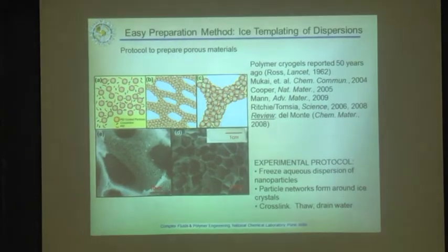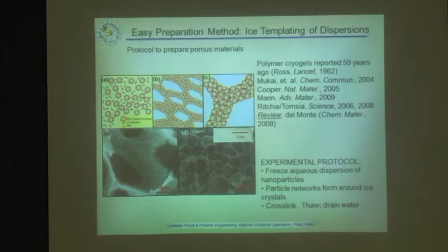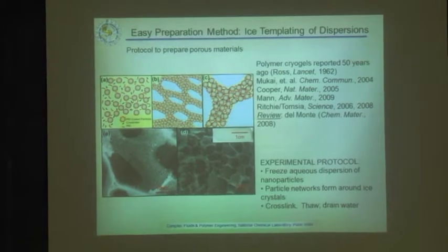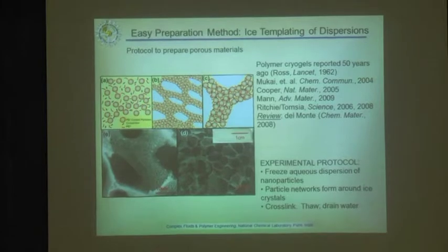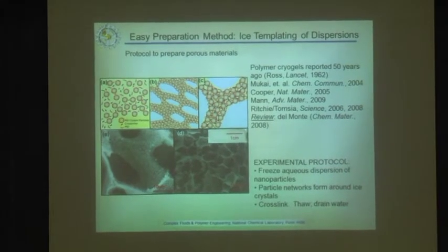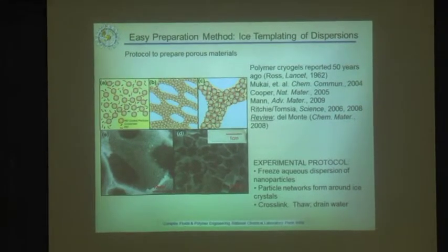The pore size also. The size of the pores might also depend on the rate at which you're freezing your... Absolutely. That is entirely dependent on how you nucleate and grow the ice crystals. And to some extent, you can control it. It's a lot more difficult to do with ice than with surfactant mesophases and so on.